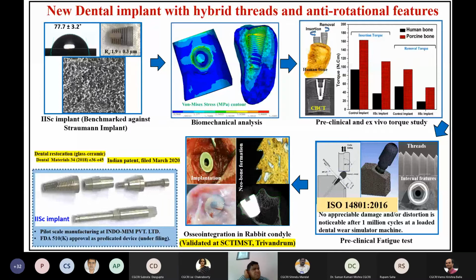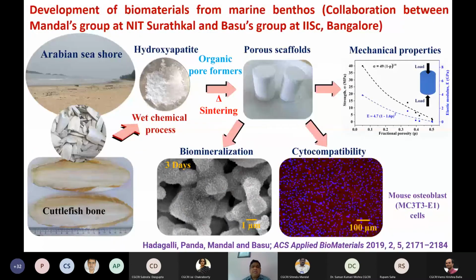inspired by so many natural resources at the Arabian seashore, I have taken this slide, which essentially shows one of those marine resources, cuttlefish bone, and cuttlefish bone derived hydroxyapatite. Essentially calcium carbonate goes to calcium oxide, then you treat it, then you make this hydroxyapatite. We have made this hydroxyapatite scaffold.